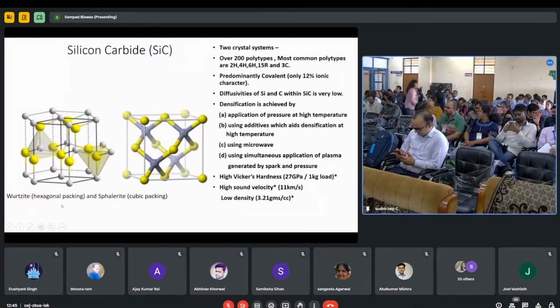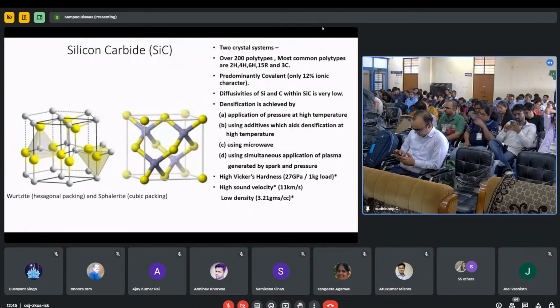it is in the hexagonal lattice. So these are the two crystal systems of the ceramics. Apart from that, it has got different polytypes also. Polytypes means the stacking of the ceramics is different. I'll show you later. Before that, I want to tell you that there are 200 polytypes of silicon carbide. So the most common polytypes are 2H, 6H, 4H, 15R, and 3C. This 3C symbolizes the cubic form. The 2H, 4H, 6H are hexagonal forms. I'll show you how it happens and what are